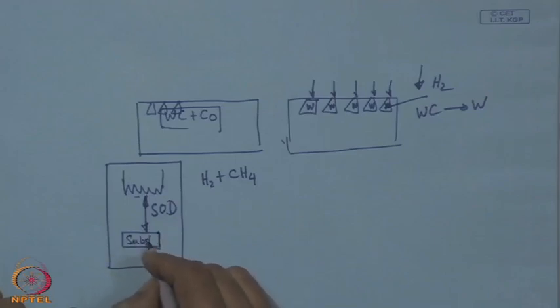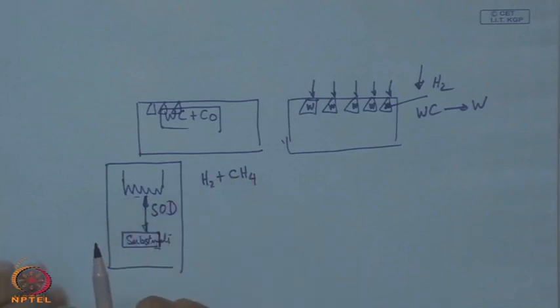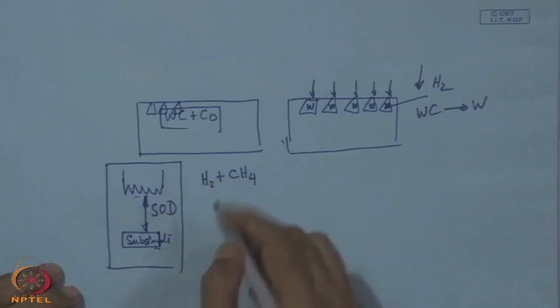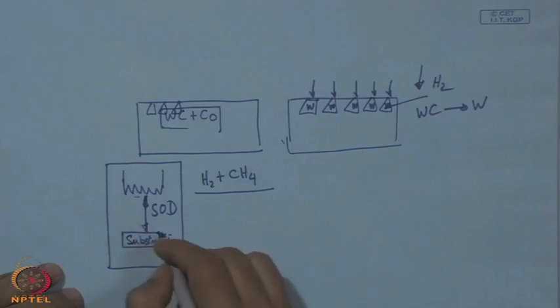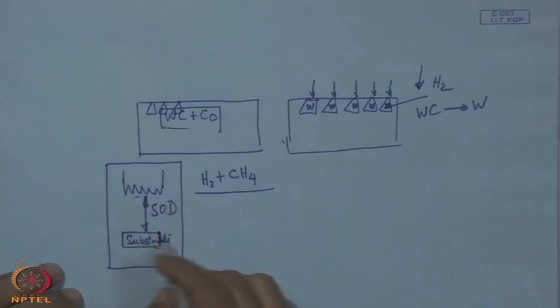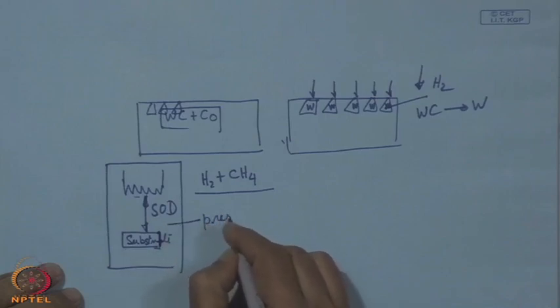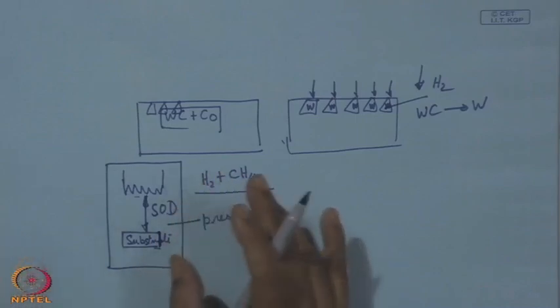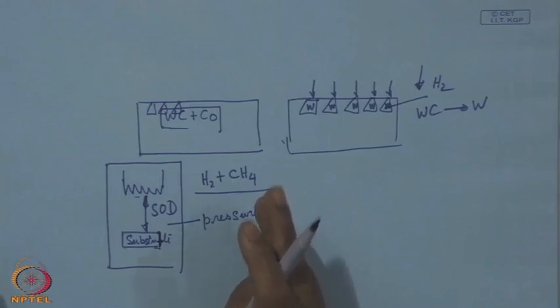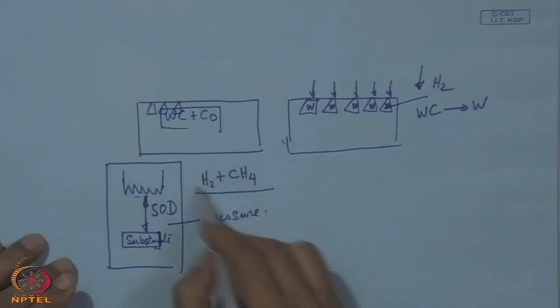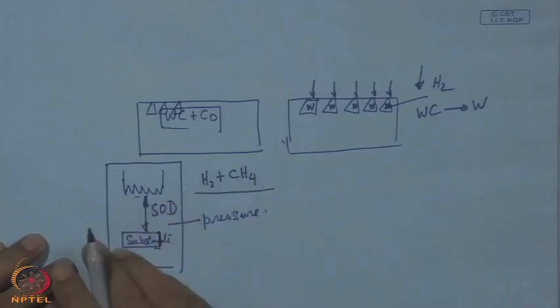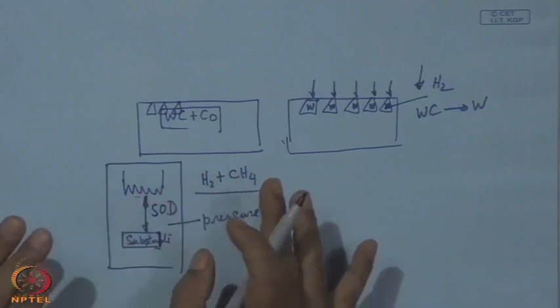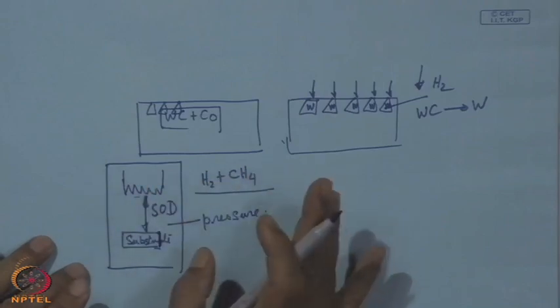This is the substrate. So, naturally the selection of this standoff distance and the selection of pressure are not independent, and accordingly the pressure and the substrate target distance have to be considered in concurrence. So, pressure and SOD have to be considered in their totality. The whole idea again is to have the impingement of this gas stream over this substrate with sufficient energy for the necessary conversion or structuring of the diamond morphology, and not to have unwanted collisions midway, so that energy is spent or lost.